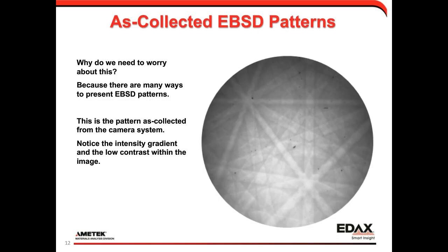EBSD patterns can look different depending on what type of processing we've used to display them. This is just an example of an as-collected EBSD pattern. This is actually just the live raw image coming from the phosphor screen with the detector inserted. You can see we see a diffraction pattern, but we also see that there's a strong intensity gradient. It's stronger toward the center, the lower center, and then it decays radially. It's generally low contrast compared to what you'll sometimes see. That's just what you actually see based on the distribution of the electrons coming out of the sample and impinging on the phosphor screen.